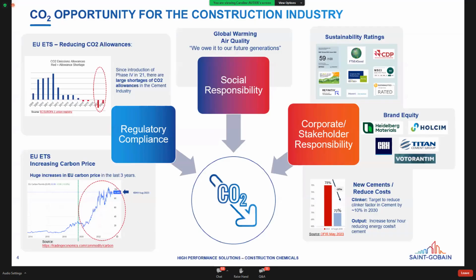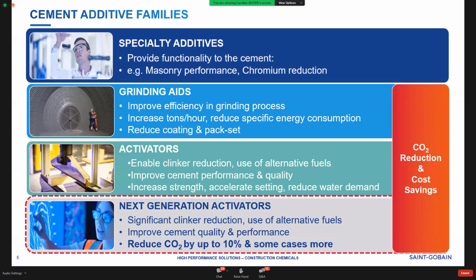On the next slide, you will see most of our product families for the cement additive portfolio, which contribute to a lower carbon footprint, resulting in cost savings, whether it be our grinding aids, which can provide efficiencies in the grinding process, for example, increasing the tons of cement produced per hour and reducing the overall energy consumption, or our activators, which enable clinker reduction or use of alternative fuels whilst maintaining the cement performances. Our new, innovative, next-generation activators can be tailor-made and adapted to suit specific cement producers' needs. These chemical activators can provide significantly higher clinker substitution, thus providing higher level of CO2 reduction as well. In some cases, this is up to 10% CO2 reduction, and in other cases, even more.